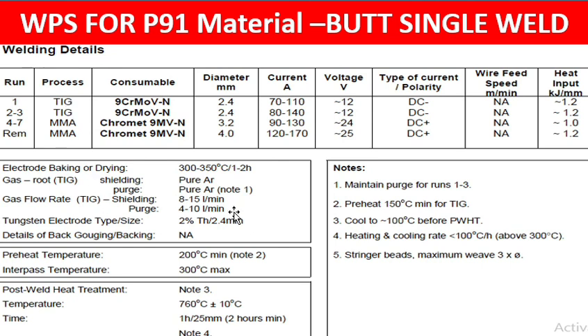Gas flow rate for shielding is 8 to 15 liters per minute. For purge, you have to provide 4 to 10 liters per minute. So for shielding, for these 3 runs 1 to 3, we have to use 8 to 15 liters per minute, and for purging 4 to 10 liters per minute. At the same time, we have to use the purge.